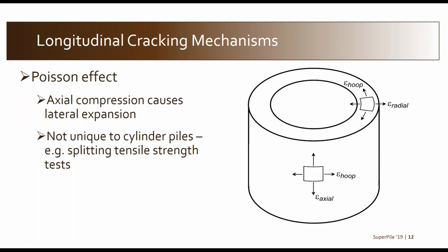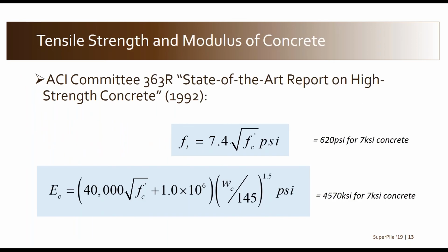And I'll point out that this is not unique to cylinder piles. In fact, there's an ASTM test designed to directly measure what's called the splitting tensile strength of concrete. And you do that by taking a concrete cylinder and loading it in compression until it splits, just like this. So we certainly can't pretend that this type of behavior is not a known mechanism. In fact, we take advantage of it and do it on purpose for that reason. So we're going to put some numbers to this mechanism and see if it could possibly explain what happened.